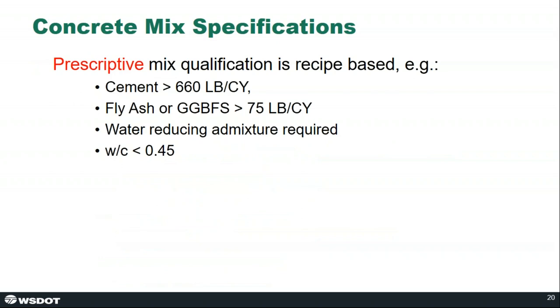So next up, I wanted to talk a little bit about how we specify our mixes in the state of Washington. And there's a couple different ways that we can go about that and that we have gone about that. One is a prescriptive type approach to qualify a mix. And it's sort of a recipe-based approach where you set a list of ranges for the constituents like you see here. We can specify a cement content of over 660 pounds per yard, fly ash over 75 pounds per yard. We can require the use of water reducers, and we can put a limit on the water to cement ratio. And these are all requirements that you typically associate with what's considered a durable concrete.